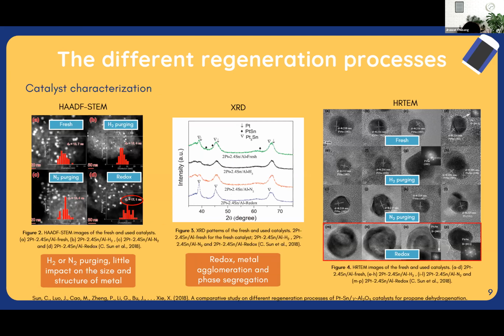HAADF-STEM image and metal particle size distribution are shown in figure 2. After 11 cycles, for the catalysts regenerated by hydrogen and nitrogen, no significant sintering emerged, whereas for the one regenerated by redox, the particle size increased to 70 nanometers. That shows this method leads to metal accumulation. Next, the XRD results show not only metal accumulation but also phase transition to Pt3Sn. The last picture shows the HRTEM image. The lattice spacing in the shell region is akin to Sn, which suggests that the metal Sn possibly constitutes the shell. This Sn encapsulation inhibits the activity.